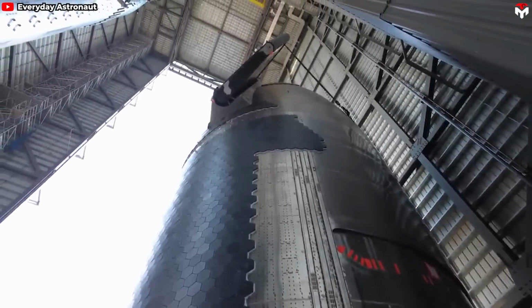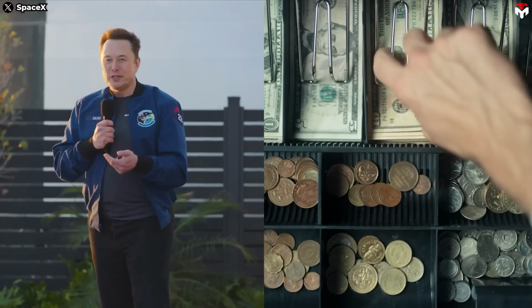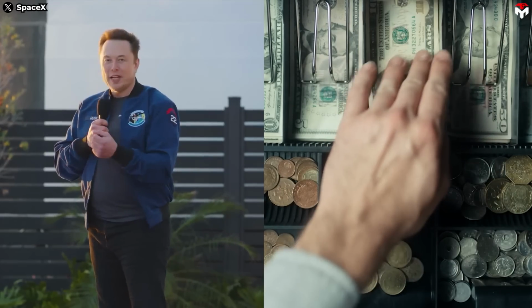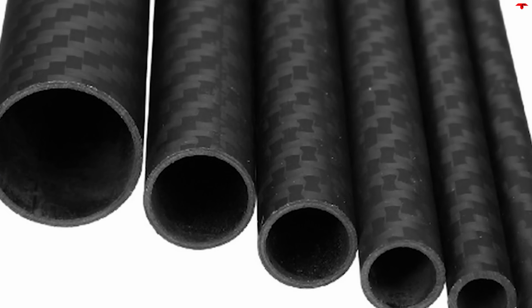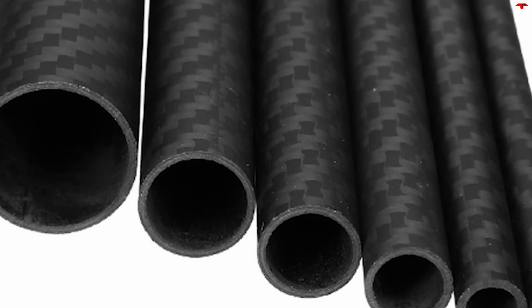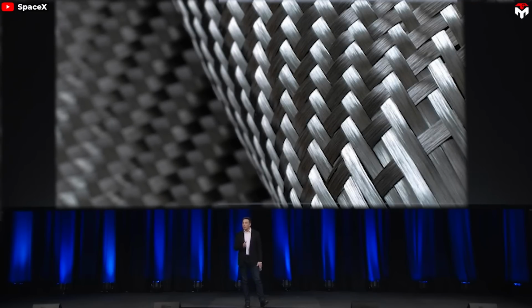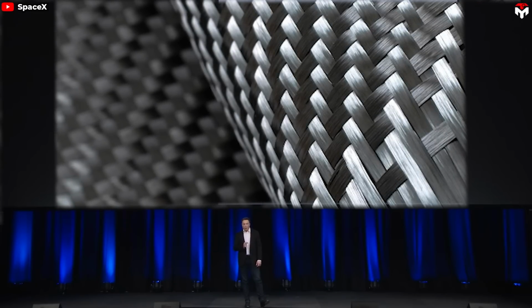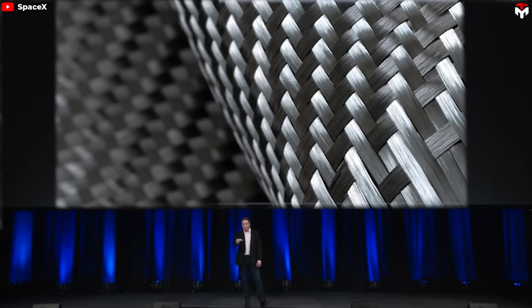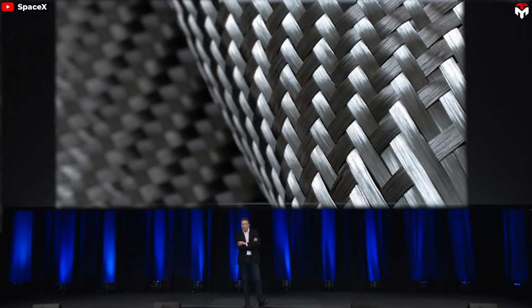And we can't overlook a very important reason: cost. You know, SpaceX's motto is cost saving. If you didn't know, carbon composite is very expensive. After cutting the fabric, it is impregnated with a high-strength resin, which is quite complex. Developing advanced carbon fiber structures takes a long time to perfect, with 60 to 120 layers of carbon fiber stacked to create the final structure. Each kilogram of carbon fiber composite costs $135, and with 35% scrap, it effectively approaches $200 a kilogram. Stainless steel, about $3 a kilogram.